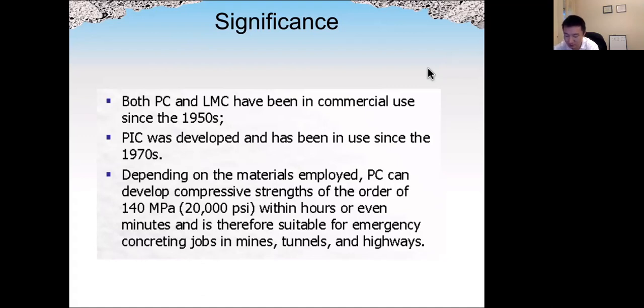The strength of polymer concrete can be very, very high, up to 20 ksi and even higher, which is around 140 megapascal. It can achieve the strength within hours or even several minutes. This is very different from traditional Portland cement concrete, which normally takes 28 days to achieve more than 90% of the final strength. Because of that, we normally use polymer concrete in emergency repair jobs.